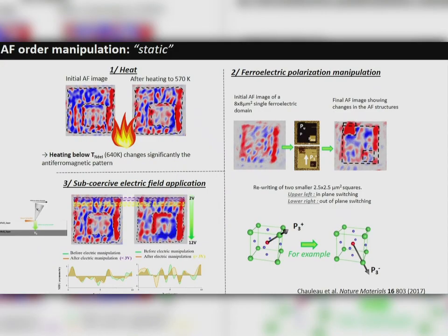Of course, we've tried several other things. We've tried to heat up the samples close to the Curie temperature, to Néel temperature, to see if it's changing. We have switched the polarizations from places to places, and we see that even in some cases, we managed to generate large single antiferromagnetic domains. That was not so easy to do and to reproduce, so we are still working on this to really fully understand what happened here. And something which is interesting here is what we have done. We have reapplied locally an electric field with the tip of this PFM by increasing the electric field and noticing at what voltage we are changing the antiferromagnetic contribution, and at a very small voltage, we're already changing it.